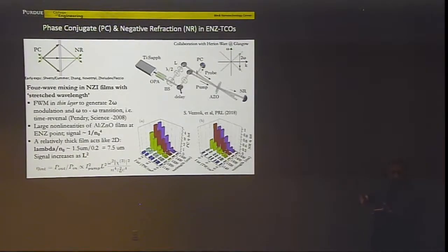a 4-wave process, you have omega minus 2 omega, which is equal to minus omega. But getting negative frequency is equivalent to getting inversion in the time domain. So this process works as a time reversal process. The only requirement is that the film should be much smaller than the wavelength. When you send the beam at omega, because of this 4-wave mixing process, you would get a beam which propagates in the opposite direction, the so-called phase conjugated beam, and a beam which propagates in the direction corresponding to negative refraction. Both beams correspond to this time reversal process.